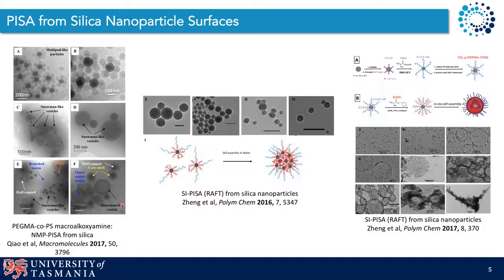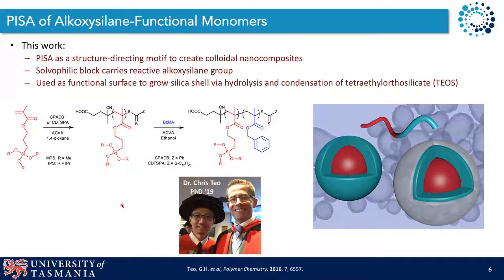There is an emergence in recent times of the idea of surface-initiated PISA from silica nanoparticles, where typically a RAFT agent is grafted to the surface. But again, we're starting with a preformed nanoparticle and we're performing surface grafting from that. What we wanted to do that was a little bit different was to use PISA primarily as a structure directing motif to create colloidal nanocomposites, where our solvophilic block carries a reactive alkoxysilane group, such as shown here: commercially available alkoxysilane methacrylates, the trimethoxysilyl version being commercially available, and the triisopropoxy version readily made in the lab. We use this as our solvophilic block to then ultimately perform chain extension with a solvophobic monomer, such as benzyl methacrylate in ethanol.